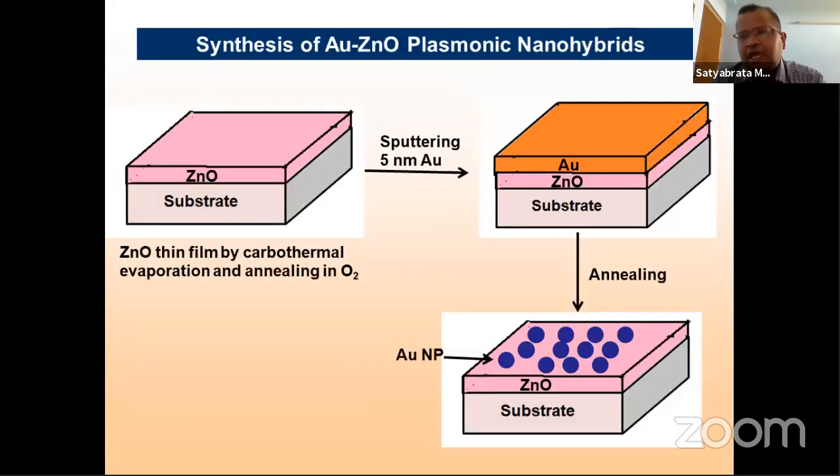Now, at the same time, it is important to see whether we can suppress the rate of recombination by using plasmonic decoration. If we integrate the plasmonic response of noble metals onto these films of metal oxides, we can do two things in one go. We can increase the light utilization capability, particularly solar light utilization, to a much higher degree, going by its plasmonic response. So the metal oxides can efficiently absorb the UV part, whereas the plasmonic nanostructures, which are integrated in the form of nanohybrids, can tap into